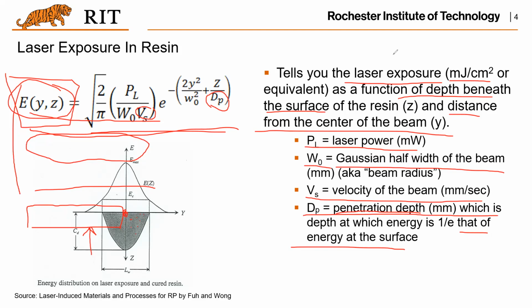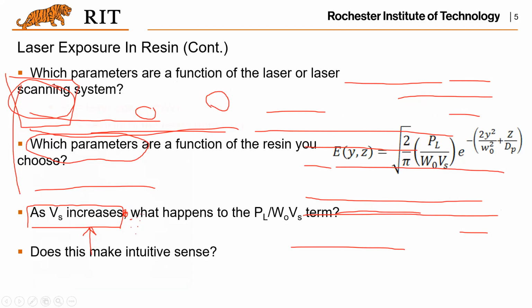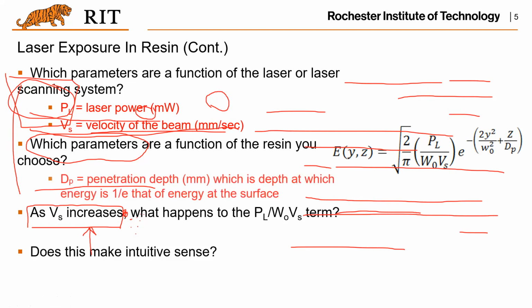And from here, you can tell the parameters are related to the laser or laser scan system. As I mentioned, the power of the laser, you can control it by changing the laser or the laser scan system. And another thing is the velocity of the beam. That is what you can control. And some other parameters are related to the resin you choose, the penetration depth, right? dp is related to the resin. For different materials, different resins, there could be different penetration depths.